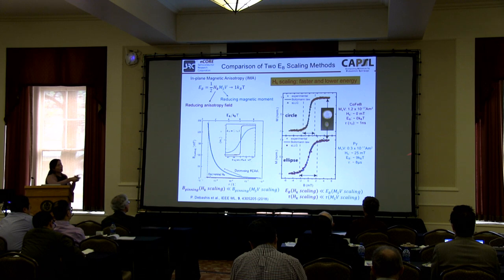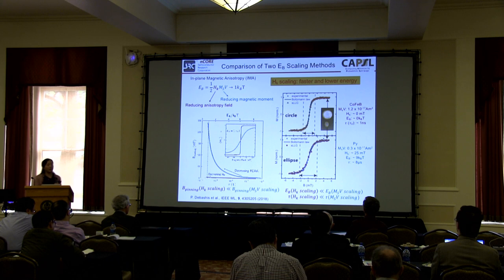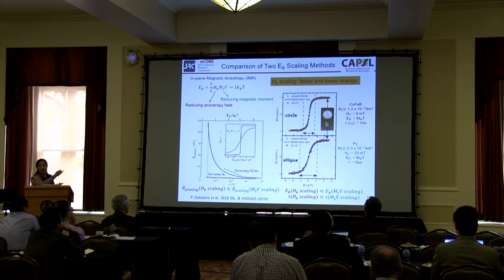I have very fast fluctuating magnets here. While the other way, when I try to make small oval shapes, because of the limitation of our lithography, we still have a rather large energy barrier here, on the 9 kT, 10 kT side. But for industry, they know how to make small magnets. I know nowadays MRAM, STT RAM is already reaching 1 GB, right? So for industry, this shouldn't be the limitation. They can easily pick either direction to scale down the energy barrier.